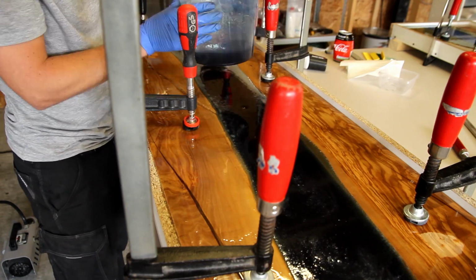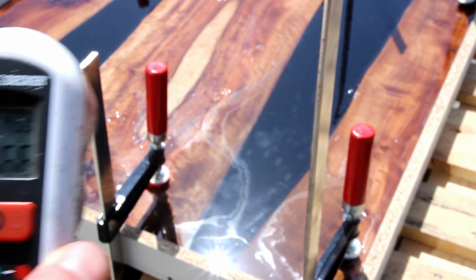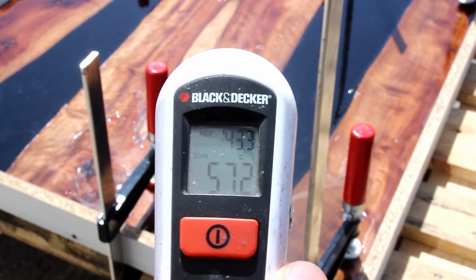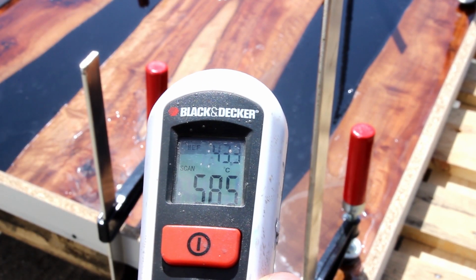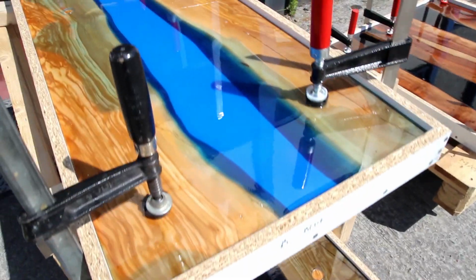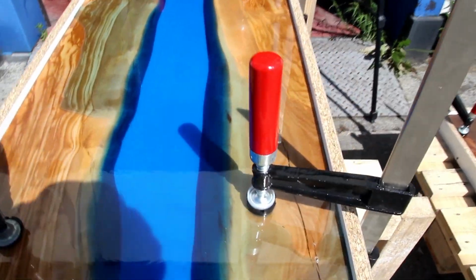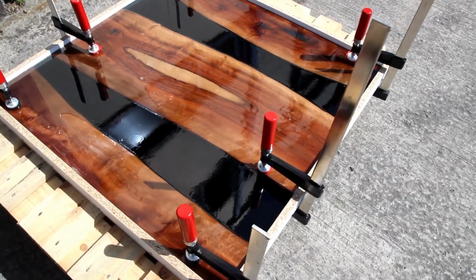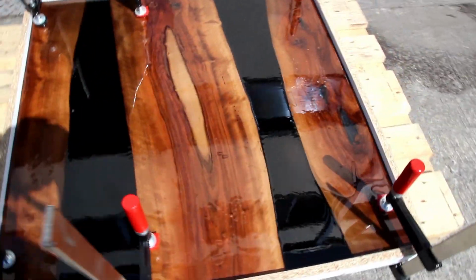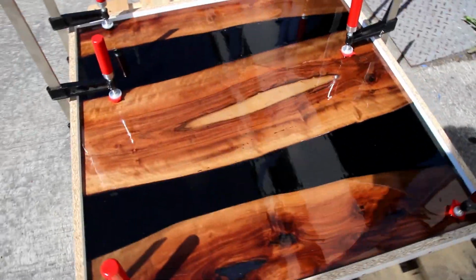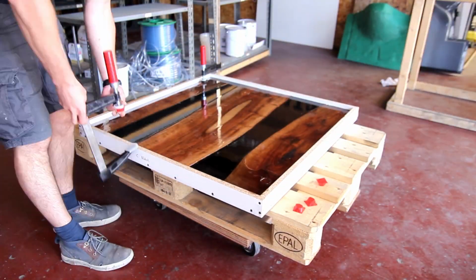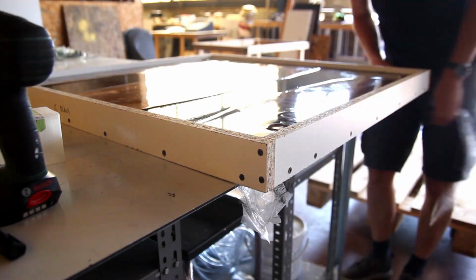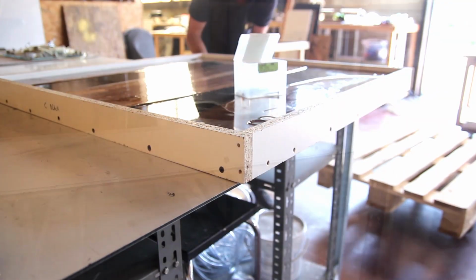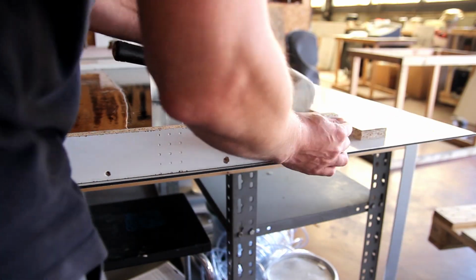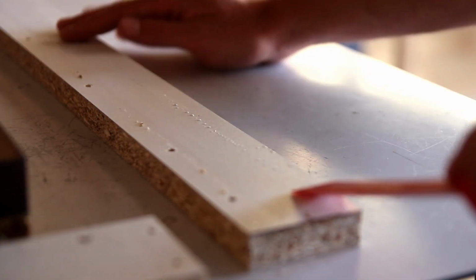Here you can see it. I'm doing this in 3 pours, which is very important. Do not do everything in 1 pour, because of the exothermic reaction. Glass Cast is a special resin that can theoretically go up to 5 centimeters in height, but it also depends on the volume you're casting. I would strongly advise you not to go over 1.5 centimeters per pour. If you measure everything, then you can calculate how much you need.